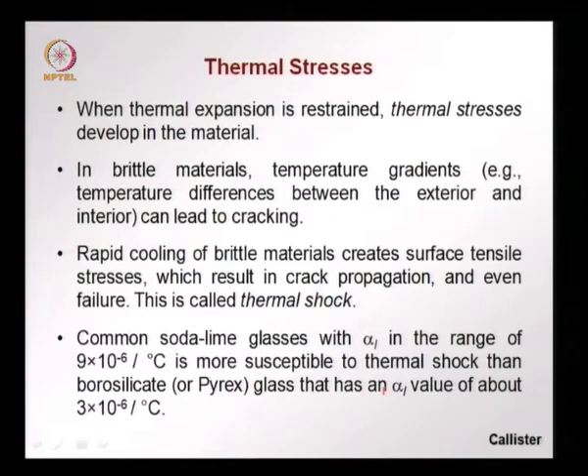Sometimes this stress is so high that the material breaks or fails, or it can cause failure in the material that is supporting it or fixing it. So, in many cases we have to worry about this thermal stresses that can be built up in a structure, and in some cases also when we combine materials, for example in the case of reinforced concrete, when we are combining steel and concrete, we choose combinations that have the same thermal expansion, so that the restraint or the differential thermal expansion does not give rise to thermal stresses, or we should not induce very high thermal stresses in any structural element that can cause failure.